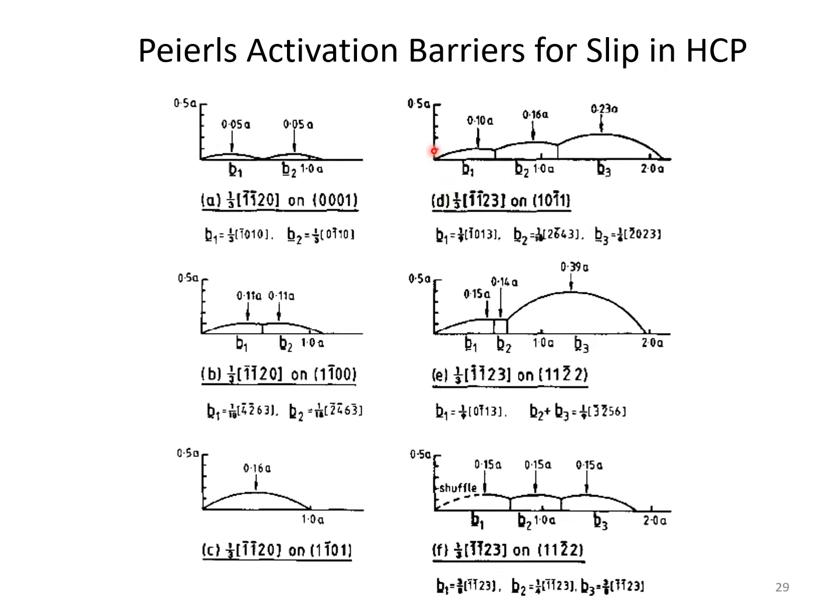Because if you have successive planes and they all go a little bit, with this partial dislocation, and then they sit comfortably at this position, that would be a twin, in fact. So you have each successive plane of atoms, another one and another one, and they can all go in the same direction.